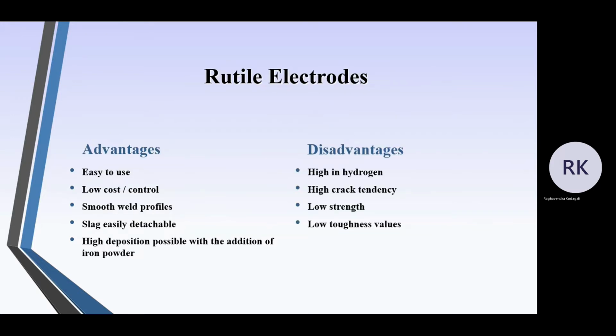So the advantages of the rutile electrode are that it is easy to use, low cost, gives a smooth weld profile, the slag is easily detachable, and high deposition is possible with the addition of iron powder. So with more addition of iron powder, you will get a higher deposition rate.